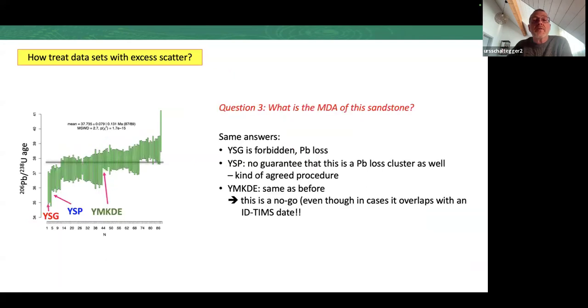Then we have the third question. What is now the maximum depositional age of this sandstone? So again, the youngest grain is forbidden, the youngest cluster probably also biased by lead loss. Again, the youngest mode of the kernel density estimate, I find is a no-go. And I even find this in a case where it overlaps with the ID-TIMS date. Maybe the ID-TIMS makes the same mistake, that we mix together very different error components and we create an artificial kernel density mode.